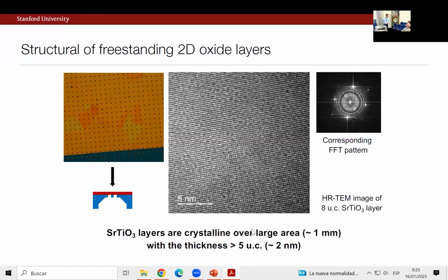So let me just show you first a few pictures and tell you a story along these lines. This was an 8-unit cell strontium titanate thick layer. We released it as a membrane in the ways that I'd mentioned to you, and we put it on a TEM grid, right? This is a very simple way to do plan view TEM, right? Almost no sample prep. We can just look right through.